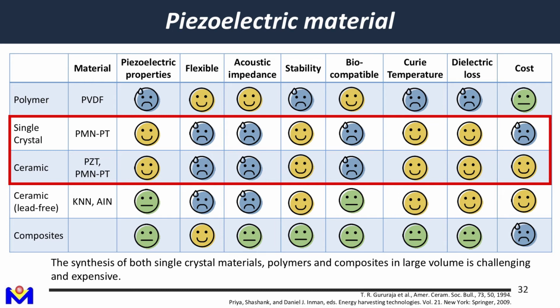So in general, of the artificial piezoelectric materials, the most popular ones are the polymer PVDF and the ceramic PZT. And of course, there is also a lot of research about lead-free ceramics, like KNN or aluminum nitride. But in general, nowadays, their piezoelectric performance, the piezoelectric constants, are still much lower than PZT or PMN-PT. This is also why PZT is a lead-containing material, but the EU has an exception to the lead-free requirement for electronic materials, because for now we cannot find a better alternative.